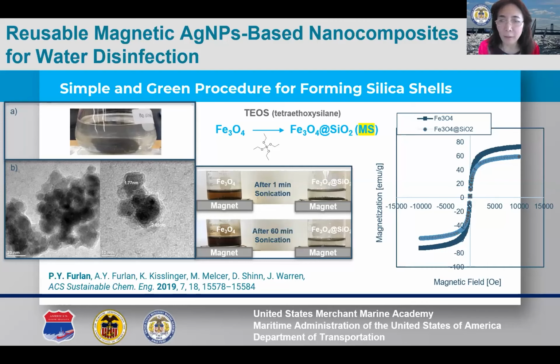In the middle figure, accelerated oxidation tests revealed that while magnetite nanoparticles became unresponsive to the magnetic field after just 1 minute of sonication in water, MS remained very responsive even after 5 days of sonication. The high magnetization and the oxidation stability were also shown to extend to products with added components and functionalities. Our approach offers substantial advantages in terms of simplicity, safety, material cost, and reduced environmental impact compared to the conventional Stöber method.